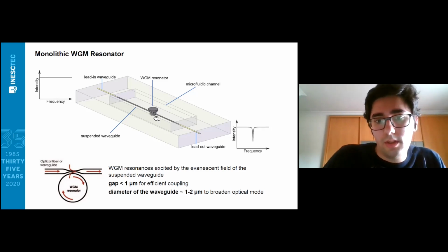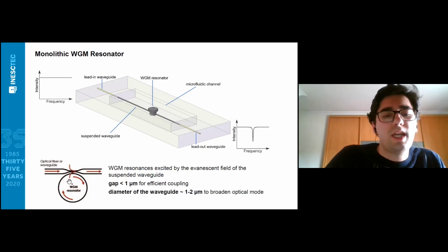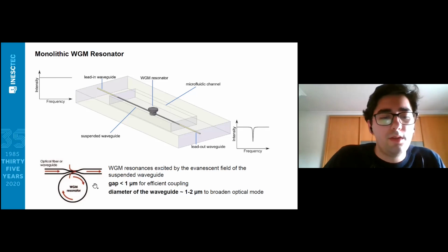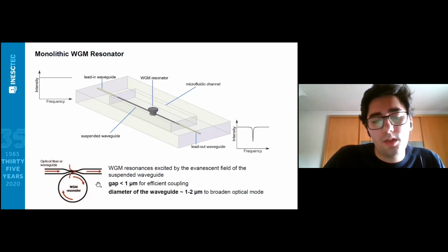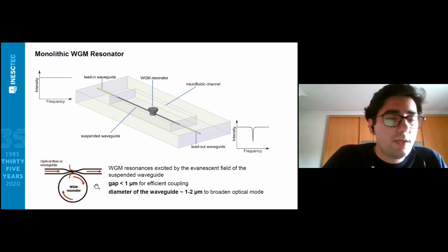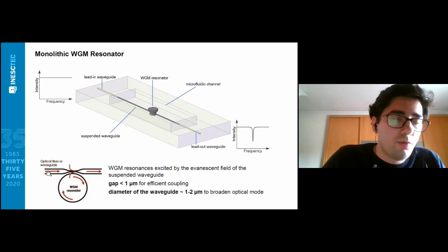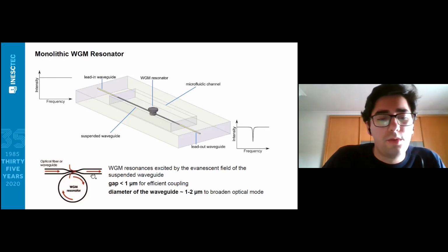To couple light from the waveguide to the microdisc, the gap between both structures in most cases is less than 1 micrometer, in order to have the mode profile of both optical modes overlap, and to also maximize the mode profile of the mode traveling through the suspended waveguide. Its diameter should be around 1 to 2 micrometers.